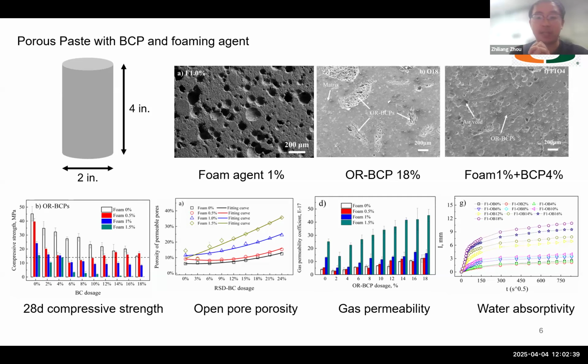The gas permeability and the water absorptivity are increased. This is because of the biochar porous. This is because the foaming agent can make a lot of bubbles inside the matrix. All of these results show the cement-based matrix became porous.